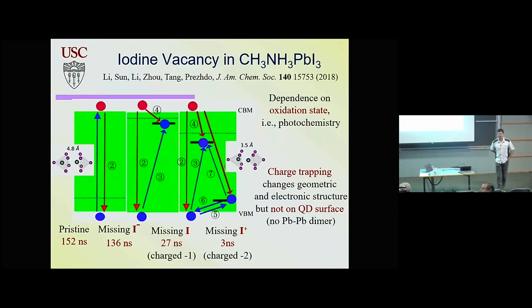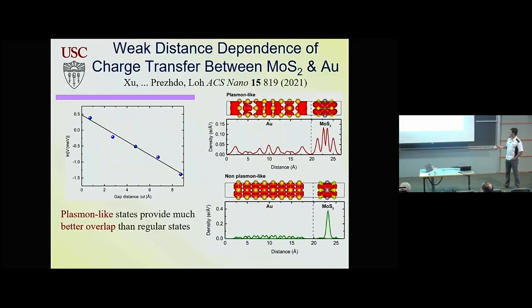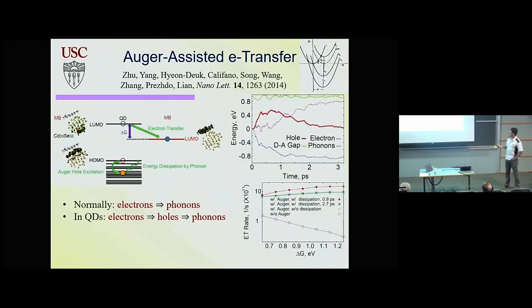I really like your explanation of the reason that there is no Marcus inverted region for quantum dots. If I understand correctly, it has to do with the density of states in the valence band, right? Right, that is very high. So I was wondering what would happen if instead of photon-induced electron transfer, you have photon-induced hole transfer. I'd say it has to do with the fact that you have an Auger process, which has two conditions. Yes, but not just the density of states: high density of states and strong Coulomb coupling, but fast Auger. You can also have Auger in that case, but the density of states in the conduction band, if I understand correctly, is not that high, right? Yeah, usually the effective mass of the hole is much heavier, so the density of states is higher. For perovskites, for these materials too.